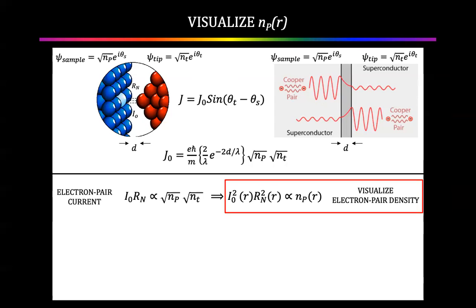So now we can integrate over this junction, Ambegaokar-Baratoff, you find out the critical current, the Josephson critical current, by the junction resistance is proportional to the order parameter in the sample, the order parameter in the tip. The order parameter in the tip is a constant. We make sure of that. So now if we square this, it should be proportional to the number density of condensed pairs in the sample at that location. That's the working idea. Measure the Josephson critical current squared as a function of location. Keep the junction resistance constant. You get a picture of the density of condensed pairs.